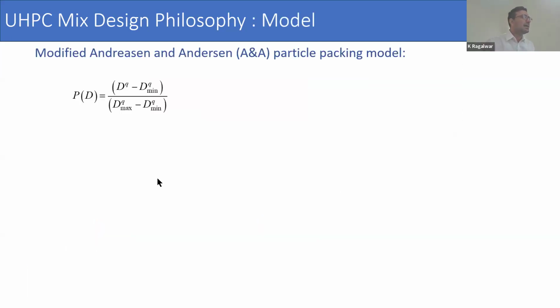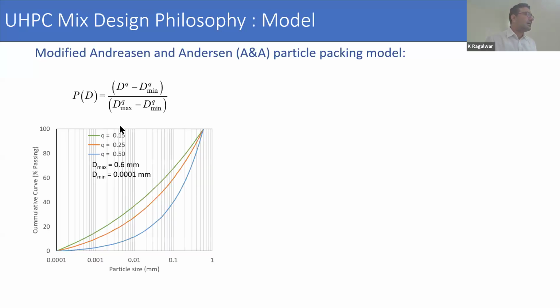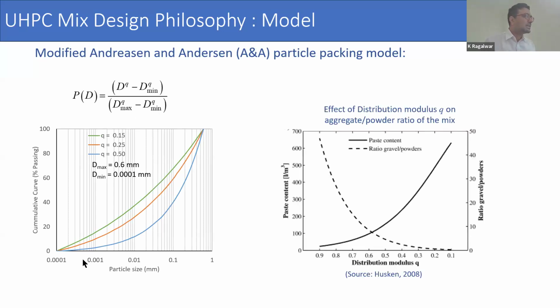During my PhD, I came up with a model that incorporates the modified Andreasen-Andersen method. So this was previously developed to look into particle packing models. What it says is that D is the aggregate size, and so the maximum aggregate size and the minimum aggregate size in the ingredients are used to determine a cumulative curve. So what these curves mean is